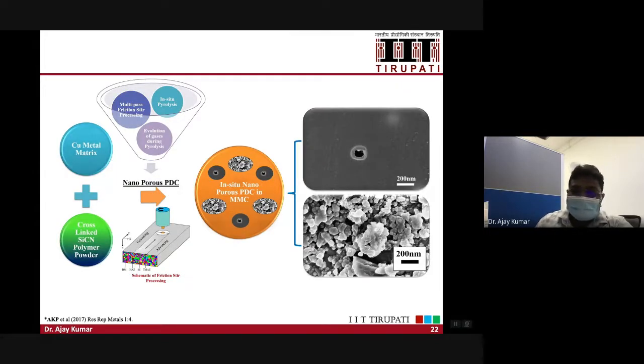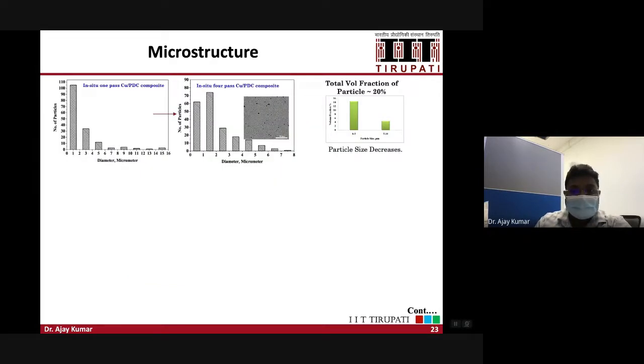So as I mentioned, during the pyrolysis you get a lot of defects or voids in the matrix material or ceramic materials. So that composite material is also useful. That material will become a metal foam, and you can use it in various applications where you need to absorb a lot of energy or shock absorption. That material will help in those applications. So we can also develop the metal foam using the same approach, and you can also get the metal matrix nanocomposites. So with one approach, you are getting two types of materials for different applications, right?